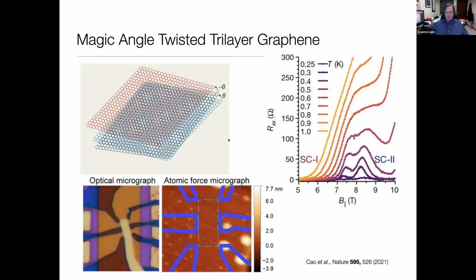And one of them, in fact, is a superconductor that you can see here. Here you see, very interestingly, the resistance at different temperatures for a certain twisted pattern. And you see, in fact, you have multiple superconducting states as a function of magnetic field. At the lowest temperatures here, you can see you have a superconducting state. A resistive state appears again, and then a second superconductor emerges at that level. And it's thought that one of these states may in fact be an unconventional state where, for example, you have spin triplet pairing rather than the usual spin singlet pairing.